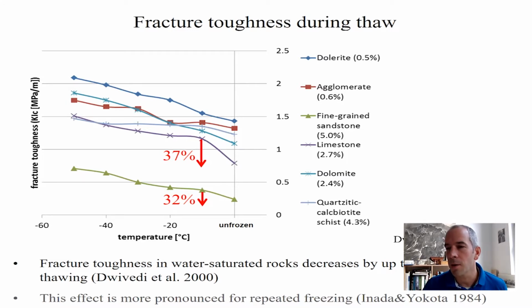So if I do that, I put my weight then on the other 9. And the other 9 have also just experienced this 37% loss in fracture toughness. So it's quite likely that the next rock bridge breaks, and then the load is too big for the other 8 and they start to break. And this is how rock slope failures start.